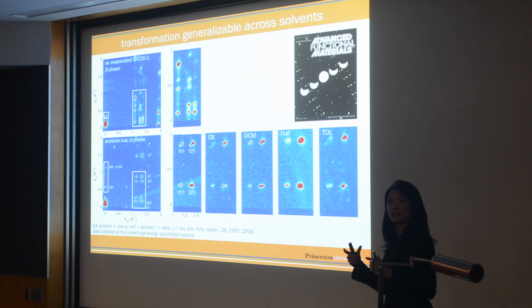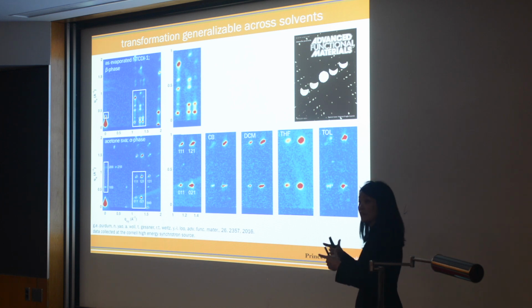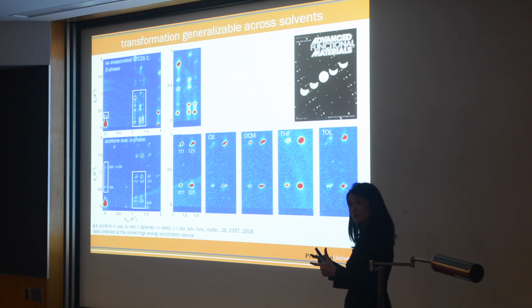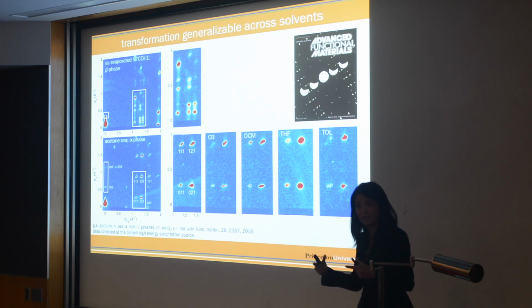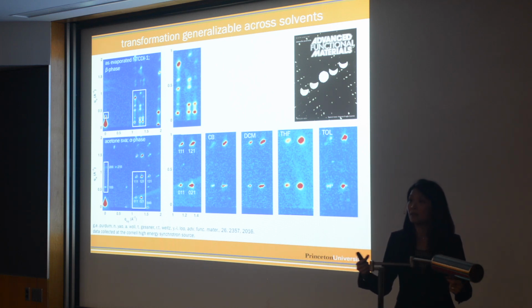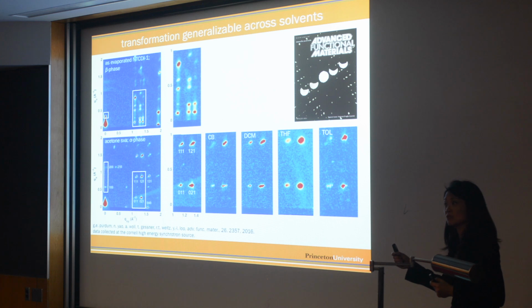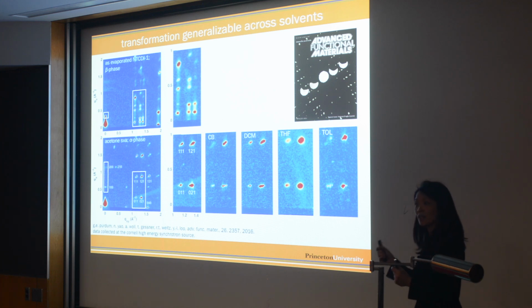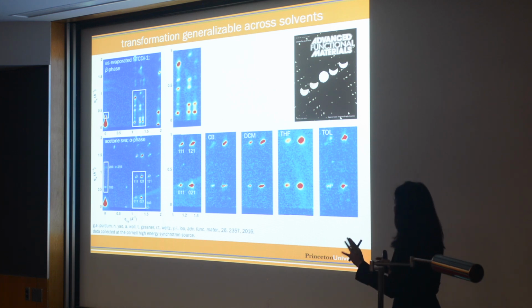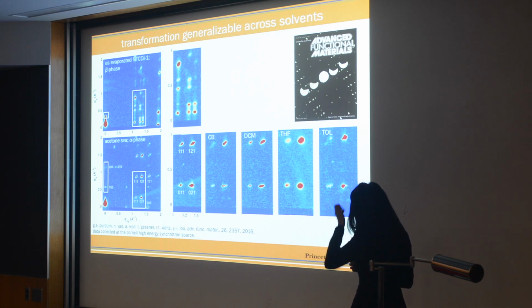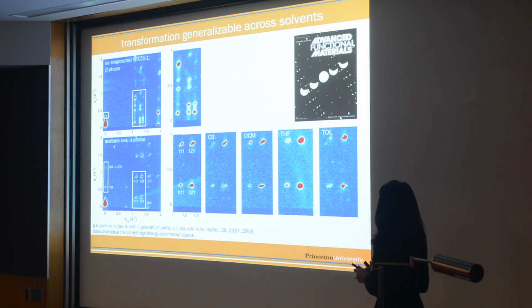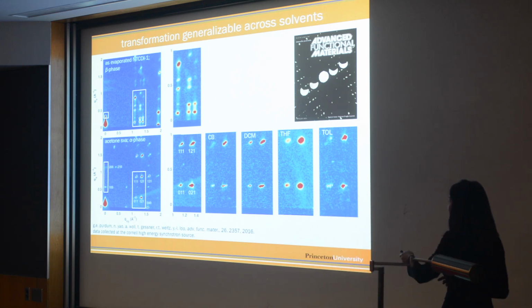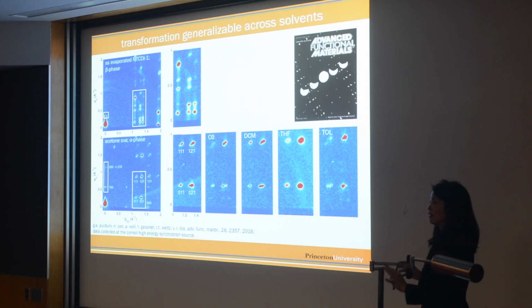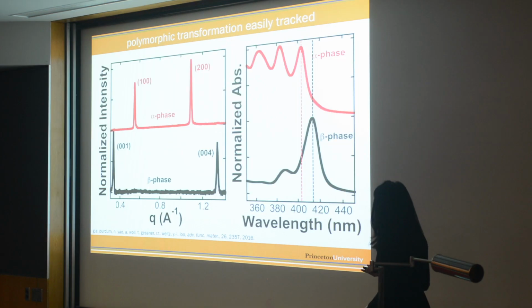So we can get different crystal habits. Sometimes we get grains when the growth rates are comparable because the growth is isotropic. Sometimes we get needles because now the pi stacking direction grows so much faster because of solvent molecule interactions. I'm not going to talk too much about that today. What I'd like to focus on is this polymorphic transformation. So in that context, all the solvents give us the alpha phase.